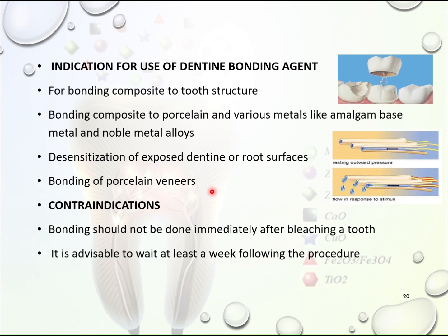What are the contraindications? If you are bleaching the tooth, after bleaching you should not use a bonding agent immediately. We should wait at least a week after applying the bleaching solution to the tooth. Otherwise, it might cause damage to the tooth structure. Also, it might cause stains in the tooth. So the bleaching would be of no use if you use a bonding agent immediately.